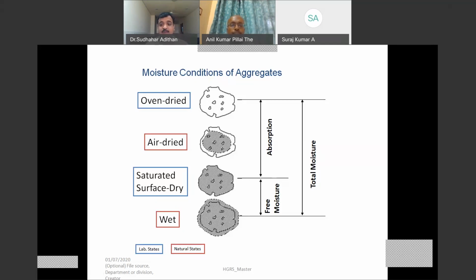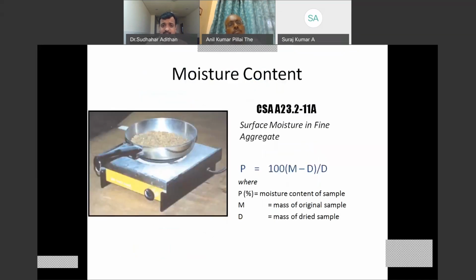It is not that you create a mix design for the primary aggregates and you just replace 10%, 20%, 30% of that with the alternate aggregates and then do the experimentation. No, if you are replacing it with 10% of alternate aggregates, you will have to see what are its implications in terms of moisture absorption, etc. Alter the mix design accordingly and then do the casting. The moisture content test, nowadays it is replaced by infrared moisture meters.